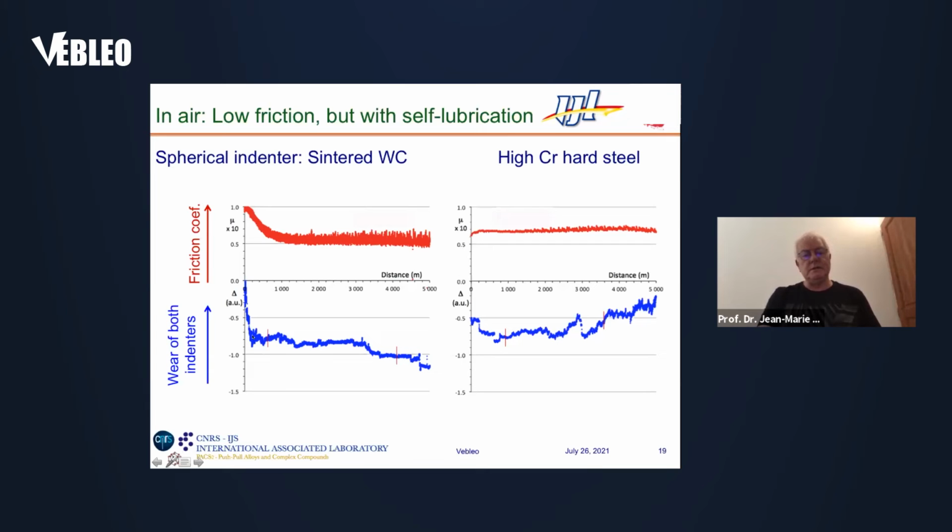So this is the initial roughness that disappears, and essentially the distance does not change anymore. And at the same time, friction is extremely small for metallic systems in contact. It is of the order of 6%. I remind you the iron on iron experiment gives you 150%, which is much higher.